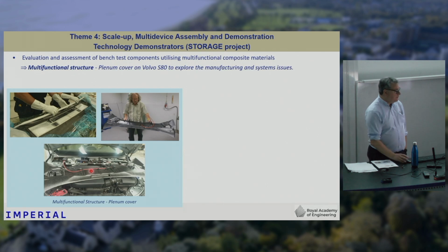So although making this carbon fiber lithium-ion battery hybrid was quite expensive, they actually recognized that the mass savings, the volume savings, and the energy savings would be significant by going down this route. And they were very keen to see this technology in use, so they actually put it into a car, drove it around Gothenburg for 18 months, and it worked fine. And it rains a lot in Gothenburg, so that didn't prove to be an issue, which was something we were worried about originally.